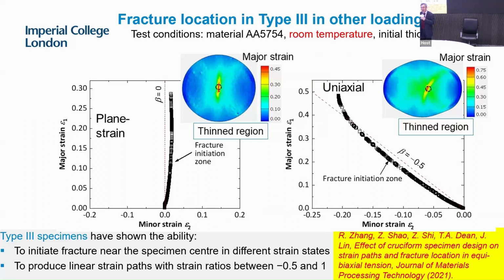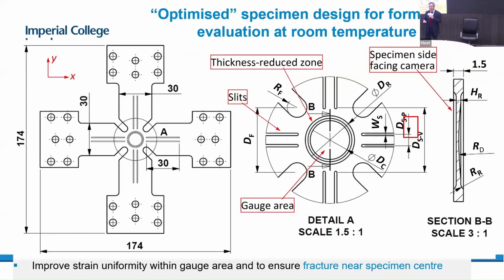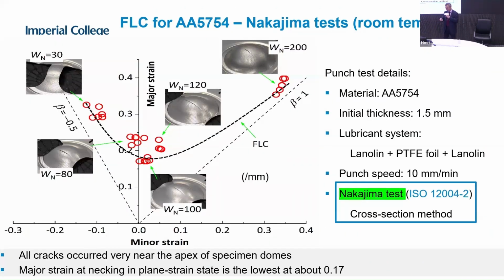We also check the loading path as well. For uniaxial and plane strain conditions, we can see all failures occur very close to the center area. Therefore, as we concluded in the previous paper I mentioned, type 3 is the recommended specimen design. What we try to do is create an international standard, including specimen design, testing procedures, and data processing conditions.